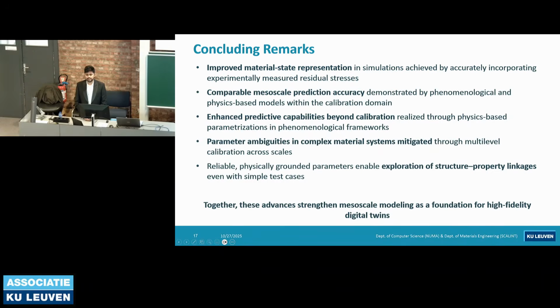Then I was also interested in the initialization. It was your first research question. I think also with microstructure simulations, it's always a challenge to have the initial microstructure correct and complete in the model. So you included the residual stresses. Do you think that was enough to have an accurate simulation? In this case, we have explicit microstructural information like grain shape and grain size, and then we implemented residual stresses, but the data was there only for a small subset of grains. So as an improvement from the experimental side, if we had data for all the grains, which is now possible with the recent characterization techniques, it would be nice to have a full-volume initialized residual stress.